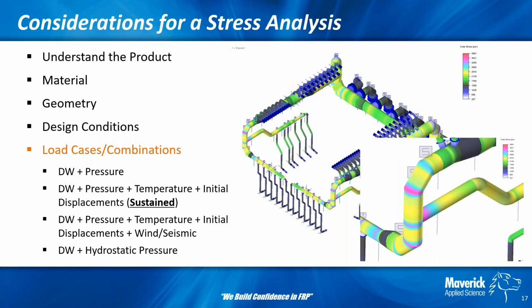What I'm showing here are recommended minimum load combinations. There are more, and it depends on what your system is. I always say dead weight plus pressure is a very good place to start. If you have elevated stress in this case, adding temperature certainly will not help your system. It's not going to make it lower stressed. So higher stress in dead weight plus pressure tells you might need supports, more supports. Maybe your spans are too long. Maybe you need a support in your riser piping somewhere. It's crucial to show here that temperature is a sustained case. It is not an expansion case.